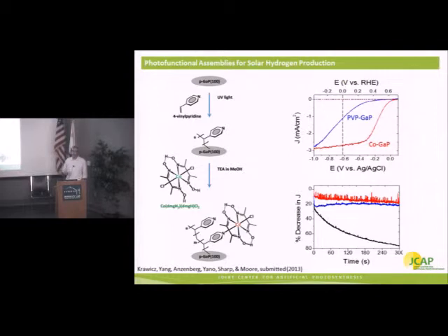However, if we shine light onto this system, again, remember we're looking at a photocathode, so the minority carriers are electrons. Those electrons will be transported through this built-in electric field to the surface, and then be transported across the interface to the catalyst and drive the proton reduction. That whole process results in an electrical current, which we can monitor or display in a way like this, with current density as a function of applied potential.